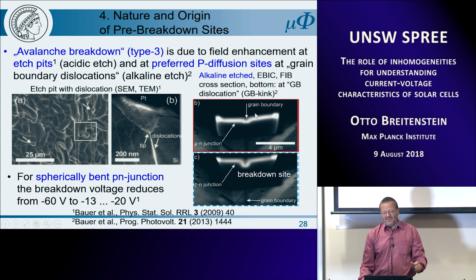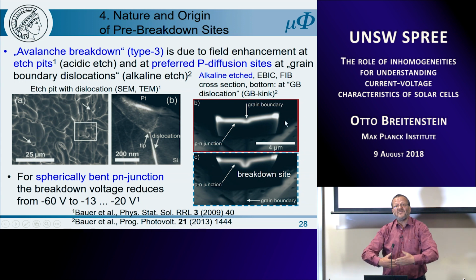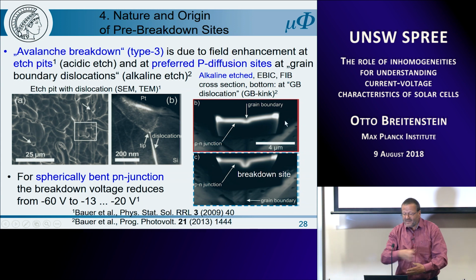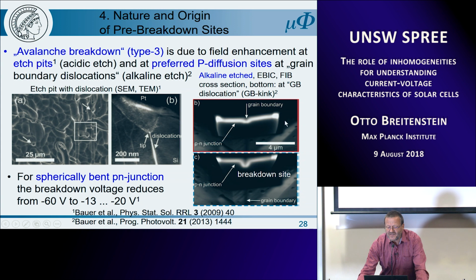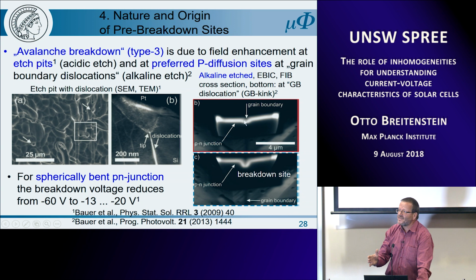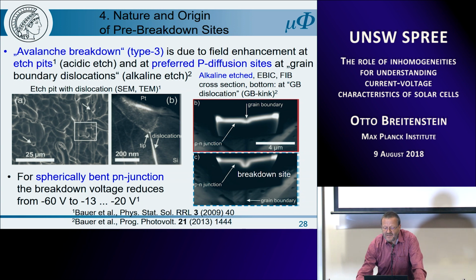And here in two positions, we have done FIB cuts and have made EBIC, electron beam induced current, on these FIB cuts. And already outside of the breakdown site, we have seen a little dip here, which means we have preferred phosphorus diffusion in this grain boundary. But in the breakdown site, it is much stronger.